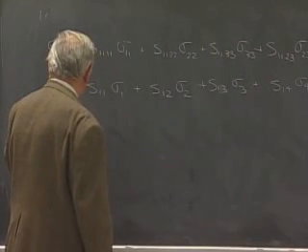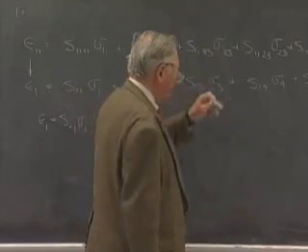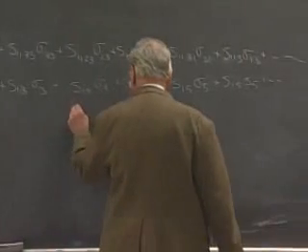So what are we going to do? Again, we're stuck. We can either say that epsilon i is equal to Sij times sigma j if j is not equal to 4, 5, or 6. Or we can absorb, again, a factor of 2 in the definition of the compliances. And that, since we will usually be working in one and the same coordinate system, is the convenient thing to do. So what we will do is to define this as S14 times sigma 4.